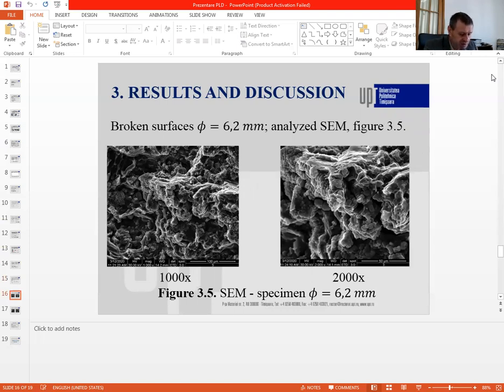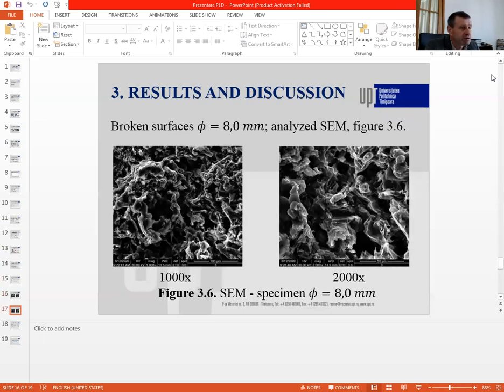The broken surfaces of the specimens were analyzed by a scanning electron microscope, SEM, for structural defects. The broken surface from the 6.2 millimeter specimen is shown in figure 3.5, and the broken surface from the 8.0 millimeter specimen is shown in figure 3.6. The material has a sponge structure with bud-like agglomerations and multiple voids.